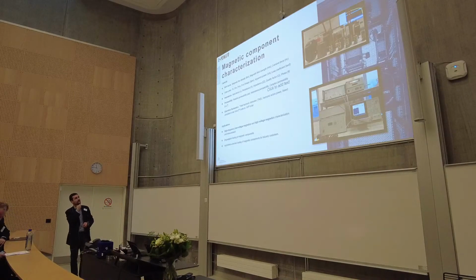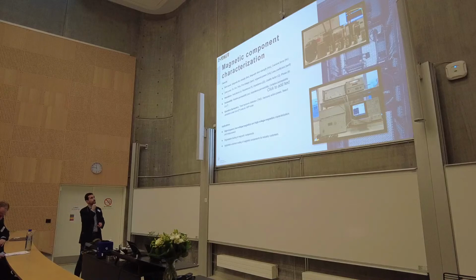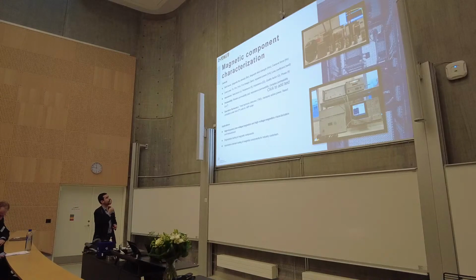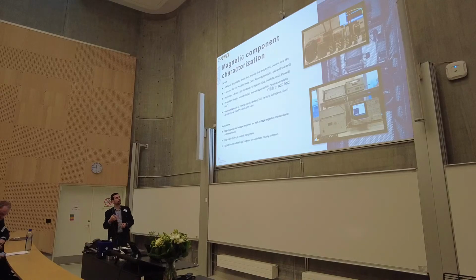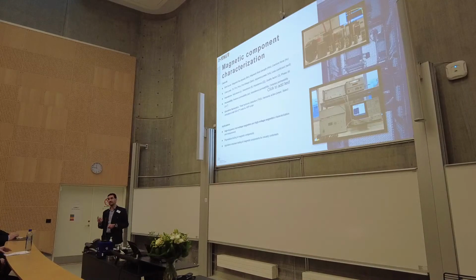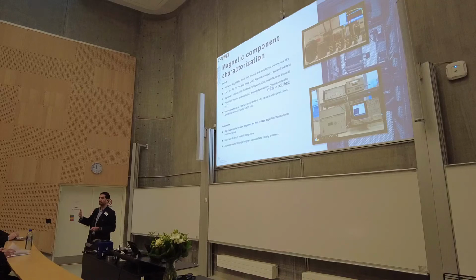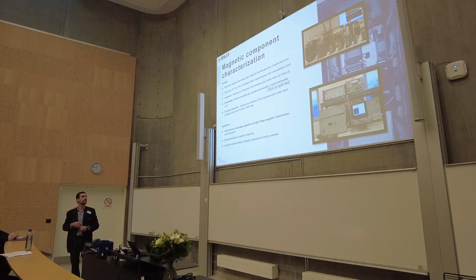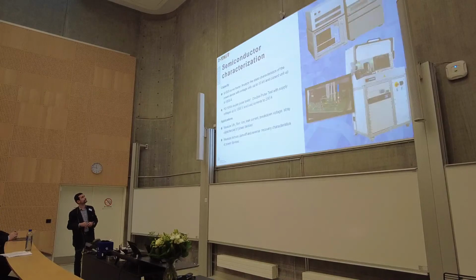Magnetic component characterization is also very important when it comes to power converters, because magnetics can also degrade. I'm talking about, of course, windings, which is the number one degradation mechanism, which is about isolation paint, but also magnetics themselves. If subjected to over temperature and something like this, they can degrade. So we are able to characterize them before and after test.